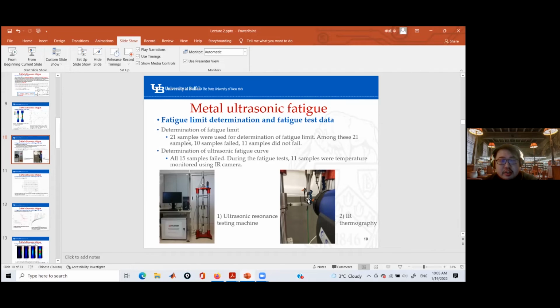Okay, so that's this instantaneous temperature. For example, it is consistently under cyclic loading, and they are consistently using this camera to monitor the instantaneous temperature change at this center during the entire testing. So they are not allowing these samples to have a cool down period. I believe this is a continuous process. Okay. Yeah. So fine.